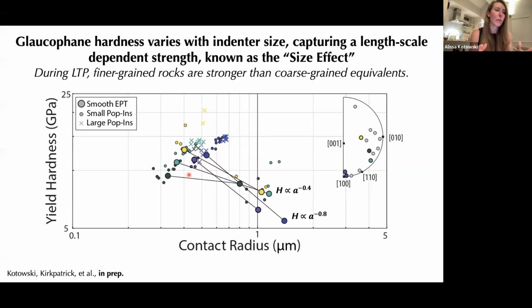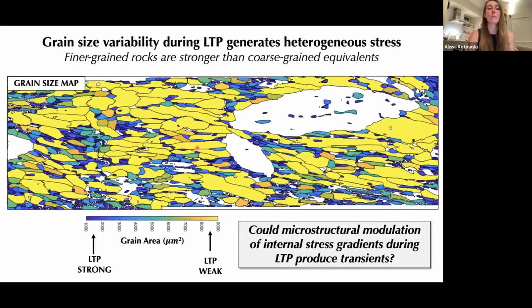So this has huge implications for deformation of texturally heterogeneous rocks, because if we have evidence that a rock is deforming by low temperature plasticity, then what this means is the finer grained portions of the rocks are actually stronger than the coarse grained portions. And an implication of the size effect is that for rocks undergoing low temperature plasticity, the grain size variability at the microscale will also imply heterogeneous stress at the grain scale. So the fine grained portions here in the blue colors will actually be stronger than the coarse grained portions. And this could, in theory, lead to stress heterogeneity during continued deformation of this microstructure.